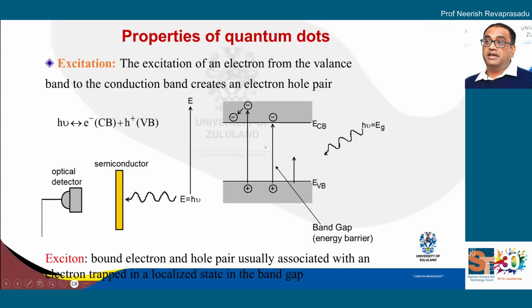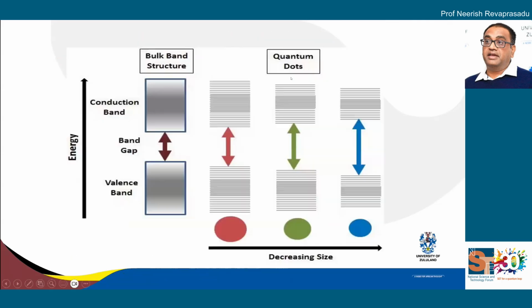Now in quantum dots, or in nanomaterials, quantum materials, this exciton, the radius between the hole and the electron, the size of your material is now equal to or less than that radius between the hole and the electron. And when that happens, you have an amazing phenomenon called a quantum size effect, where you have an increase in the band gap of the material. And that is shown in the next slide.